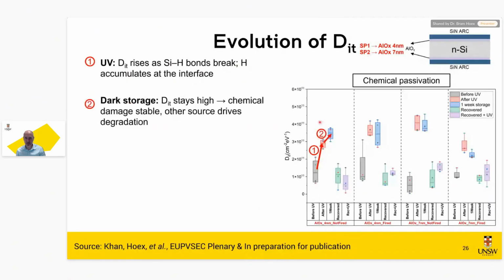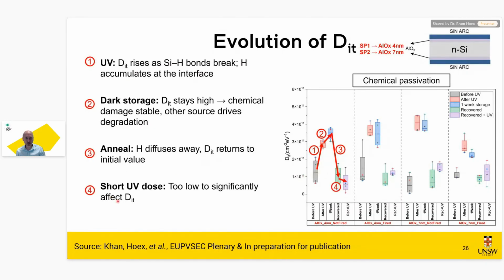In the dark, we see that for most samples, so here we see a slight increase, but most samples we see DIT staying equal. So there's nothing happening with DIT when you put the samples in the dark. So that's a very important observation. It's also not improving. It stays stable. If we do the annealing, so that's the green curve here, we see that we improve the DIT. So we fix the interface, and we attribute that to hydrogen diffusing away from the interface, and we can see that we're back to square one. And then a short UV dose, as you would use in stabilizing before measurement, doesn't really do anything for DIT. So it means we have part of the puzzle, but we don't have the full puzzle for DIT, if we just focus on DIT.